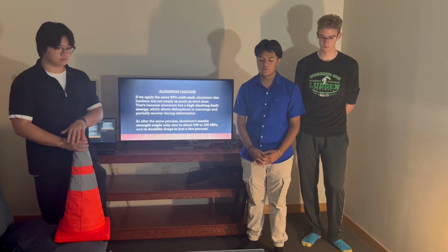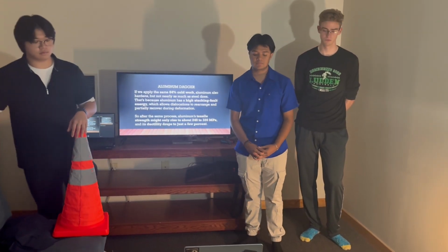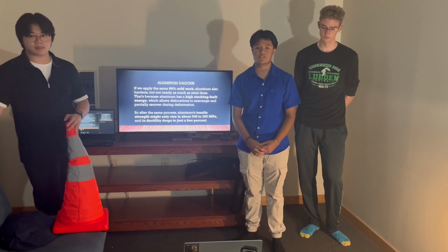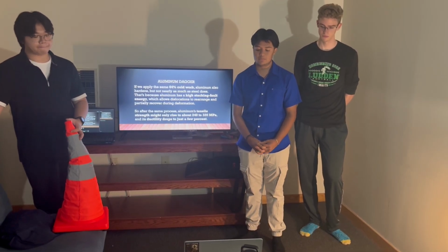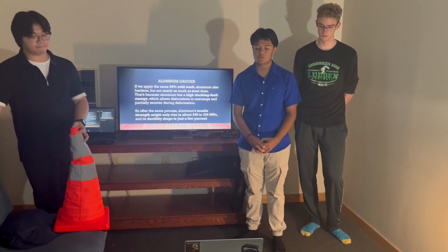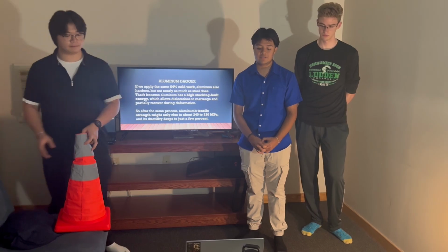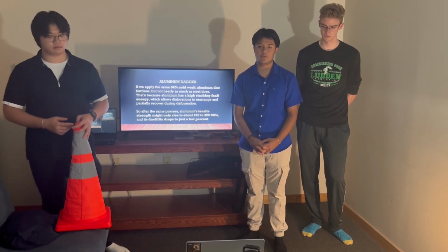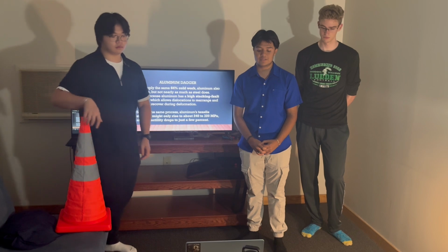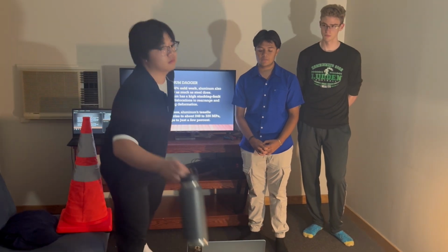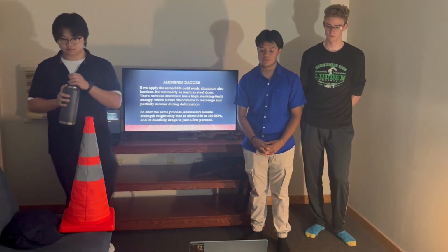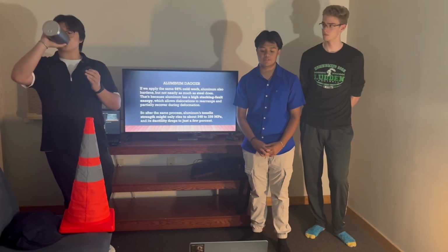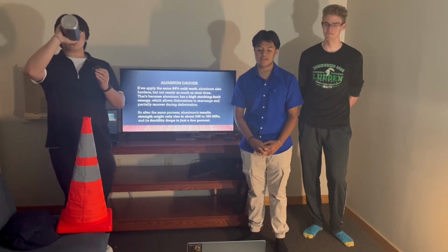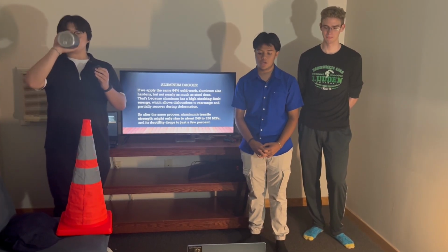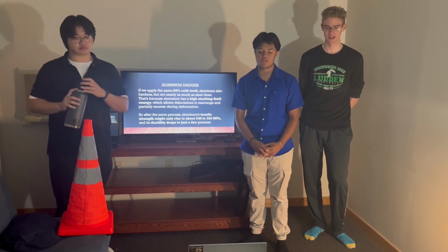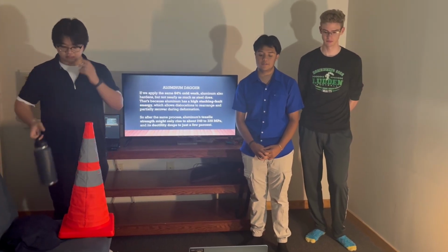Now, let's look at aluminum under the same process. Aluminum starts off much softer. For example, an annealed 6061 aluminum alloy might have a tensile strength around 200 megapascal. If we apply the same 64% cold work, aluminum also hardens, but not nearly as much as steel does. That's because aluminum has a high stacking fault energy, which allows dislocation to rearrange and partially recover during deformation.